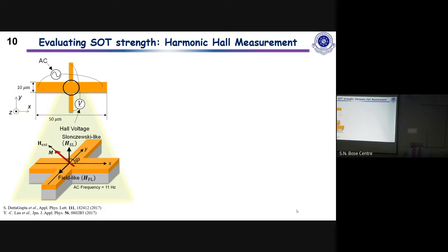The advantage is that this is a transport technique. So you can just make a device. A big one also is okay. It doesn't necessarily have to be 10 microns. It can be 50 microns or 100 microns. Just take 4 contacts and put it in a PPMS or any other machine and just measure.